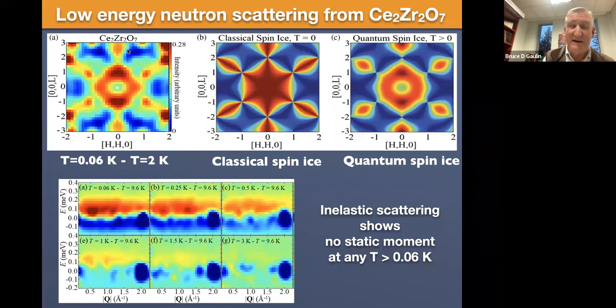Okay, so neither the experiment nor any of the theories that we're going to compare to have any Bragg peaks. They're all very disordered looking structure factors. But classical spin ice has, even though all the scattering is diffuse, it's all very blobby in reciprocal space. It has these very interesting features which are called pinch points, which you can see here. There are regions where these two blobby components of scattering come together and sort of kiss. And so it's a rather sharp feature, but it's only a sharp feature in one dimension.